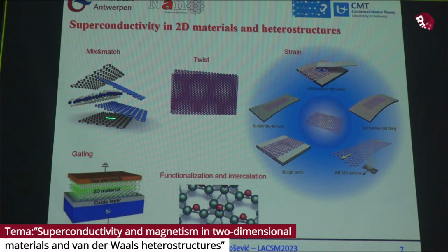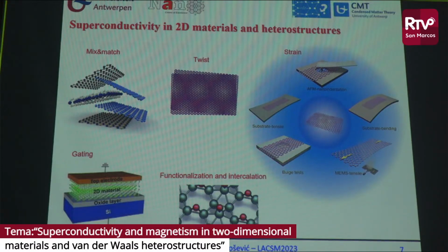Mixing and matching different 2D materials and heterostructures is perfectly feasible. A twist between two monolayers of a material induces new phenomena. I'm sure you know about superconductivity emerging in twisted bilayer graphene. Strain: these 2D materials can be strained much more than their bulk counterparts, thereby you can affect superconductivity much more than in bulk by using strain.